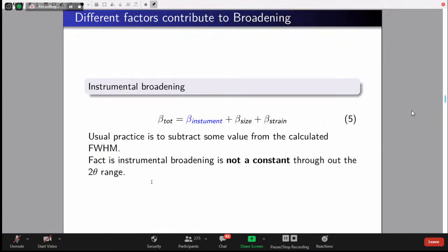So we will just sort out what the possibilities are where the instrument can contribute to the broadening. Forget about the crystallite size and the strain. The instrument itself has a broadening, and this broadening is not a constant, because in the Scherrer formula we say just subtract the instrumental broadening of 0.01 or 0.001 or something, and we will start calculating. But this width is not a constant. It varies with the 2 theta values.